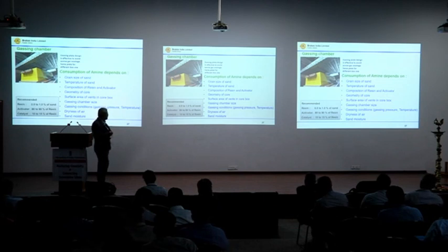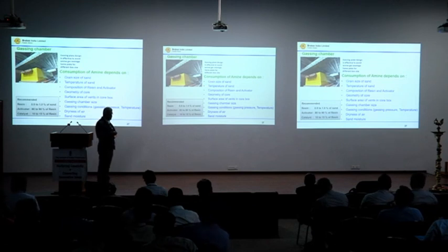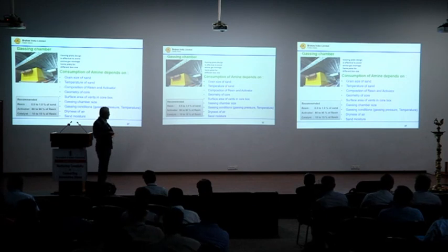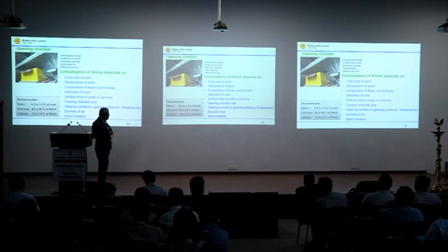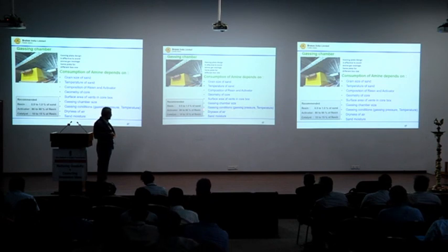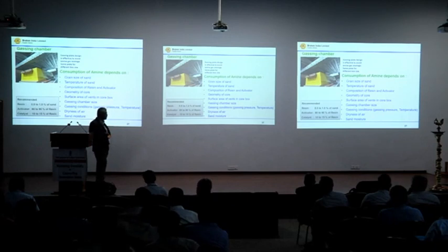So the following is important to control the amine consumption: grain size of the sand, temperature of the sand, composition of resin and activator, geometry of the core, surface area of the vents and the core boxes, gassing chamber size, gassing condition - that is gassing pressure and temperature, dryness of air, and sand moisture. These are all the important things for amine control.